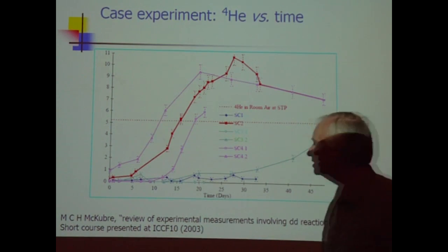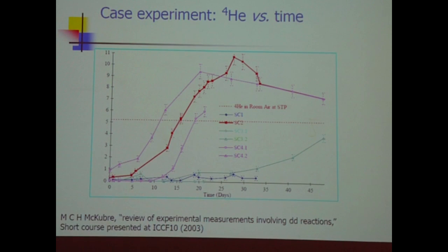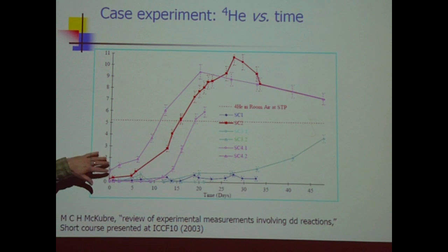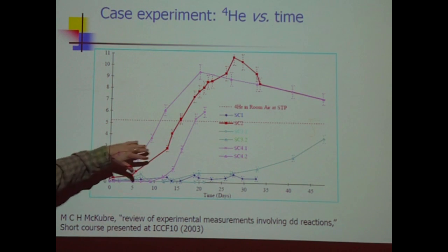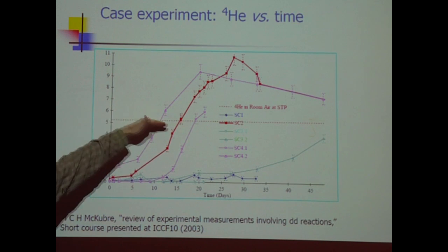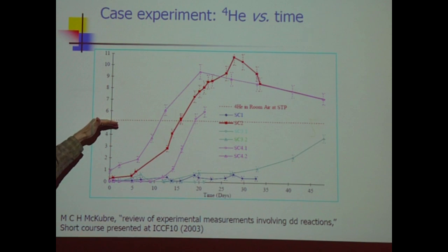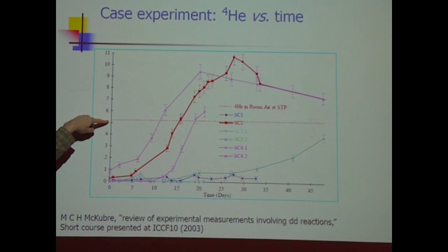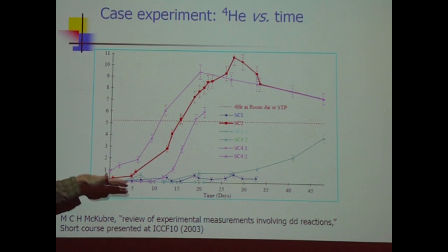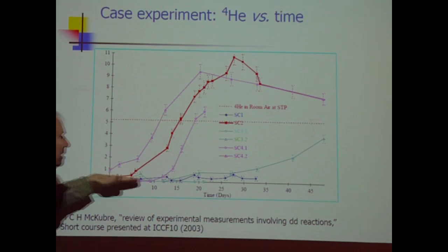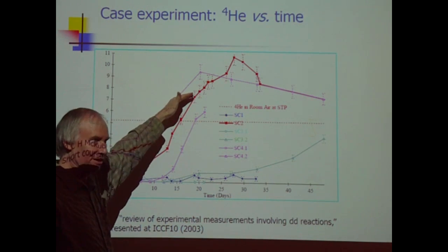This is an example of the helium-4 measured during an experiment. So several experiments. So what was observed is helium-4 was produced. This is the level of helium-4 due to atmospheric contamination. So this is 5.2 parts per million inside the cell. There's less of that to start out with. Helium-4 is liberated in an amount that's larger, and then it starts to go away.